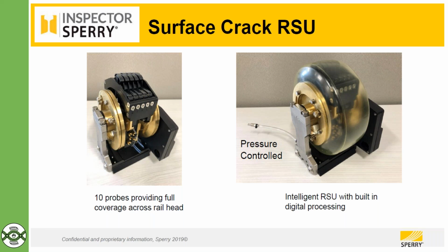10 probes which are close to the rail are now constantly pressurised to maintain the correct pressure, so you get the right footprint, you avoid any leakage and punctures. You can also detect if there's any problems. So something we think will have a significant improvement in the quality of the data and repeatability of the data, as well as reliability of the equipment, so less lost testing. So that's now fitted to our vehicles and it's been rolled out on 6th September.